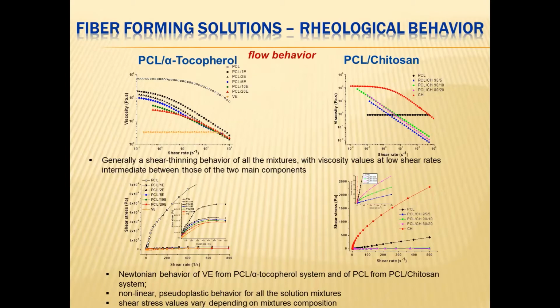The shape of the shear stress, shear rate curves show clearly the Newtonian behavior of vitamin E in the first case and of PCL in the second case, with the shear stress increasing linearly with the shear rate, as compared with the non-linear pseudoplastic behavior for the other solution mixtures. Also, it's observed that shear stress values vary depending on the mixture's composition.